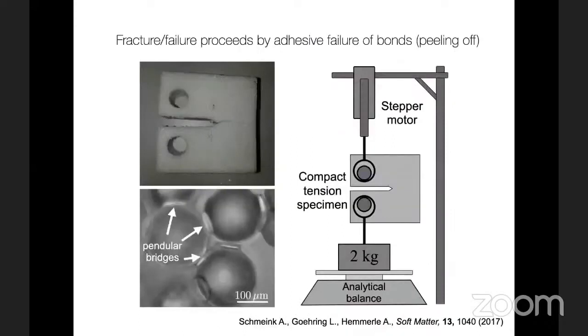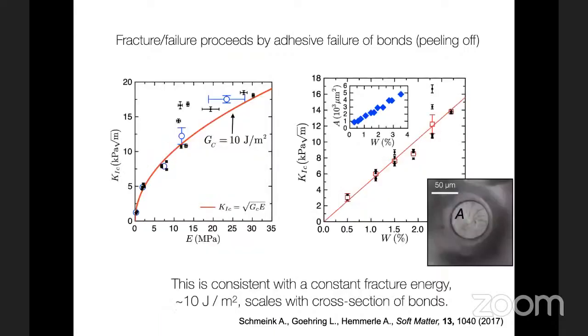We can also do fracture tests. So the second paper in the series was measuring the fracture properties of this. And we find, again, those are tunable. So we can do these with standard test samples. In this case, it's under tension rather than compression. But the failure mechanisms are similarly brittle. It develops a fracture. What we find is the fracture propagates by the bonds peeling off or losing cohesion with the particles. And we can characterize that by a Griffith-like condition, where there's a fracture energy associated with the area of the bonds.